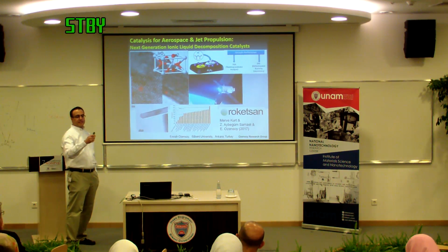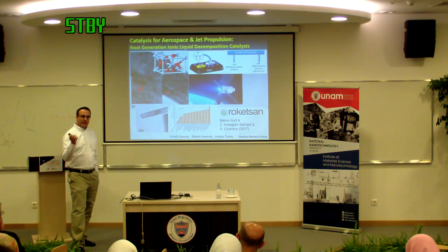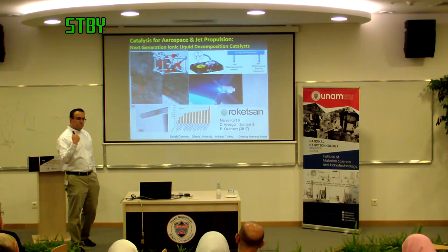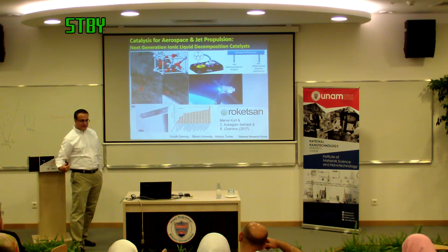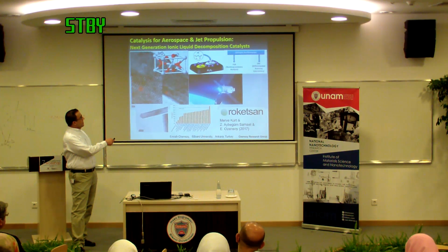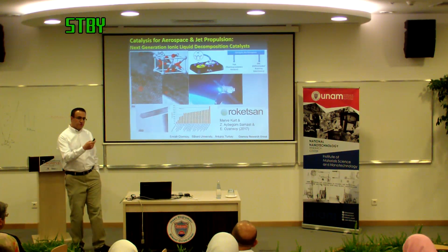Actually, surprisingly, the chemistry is very similar to emission control systems. We don't tell them to look at something. But actually, it's oxidation chemistry in the absence of oxygen. So what we use is we actually add some ceria and lanthana. These are oxygen pumps. That means they can take oxygen into their lattice and they can pump out the oxygen from the lattice by generating some oxygen vacancies. When it decomposes, oxygen is stored in the solid. And then when you're deficient of oxygen, the solid just kicks out oxygen and you can actually do redox chemistry in space, in the absence of oxygen. And it works relatively fine.